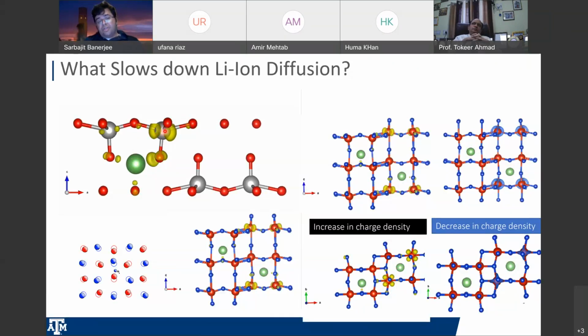And because the electron is localizing, it's not spreading out, it's not delocalizing, right? Because the electron is localizing, the lattice actually slightly distorts, and that distortion of the lattice and its electron is called a polaron. And that polaron binds the lithium ion, and this is called self-trapping. So the polaron, which is the electron plus the lattice distortion, can be a little bit more difficult to move than a delocalized electron, or a lot more difficult to move. And then the self-trapping of the lithium ion also makes ionic diffusion difficult, right? So essentially, polaron formation is a major problem to the diffusion of lithium ions and electrons in the lattice.